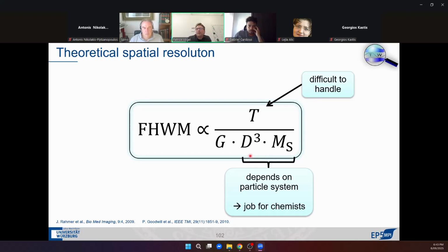I said the best particle size is between 20 to 25 nanometers. Why are we not using 100 nanometer particles? Well, because you can remember the Brownian relaxation. The problem is when you're using large particles, the particles cannot follow the external magnetic field in real time anymore, and thus the image starts to blur, and you will also lose spatial resolution.